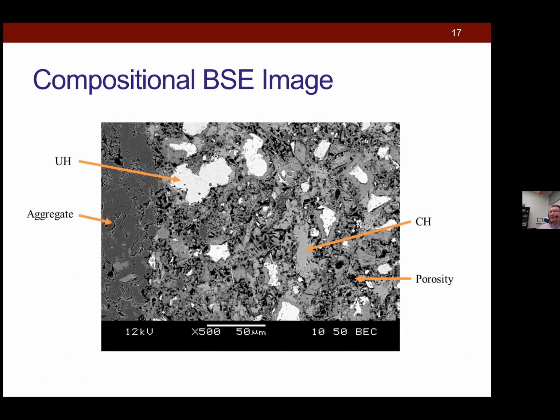So to study the ITZ, you first have to epoxy impregnate your sample. You have to fill in that void space with epoxy so that you're stabilizing the microstructure, and then you have to polish it fairly flat. Then you're going to do scanning electron microscopy, specifically backscattered electron imaging, and based on the grayscale, you can start to pull out different components of the microstructure. And then you can start to look at the distribution of these phases as a function of distance from the aggregate interface.